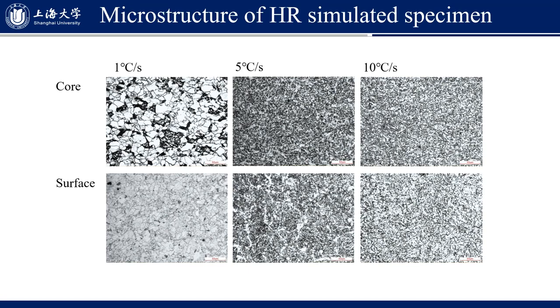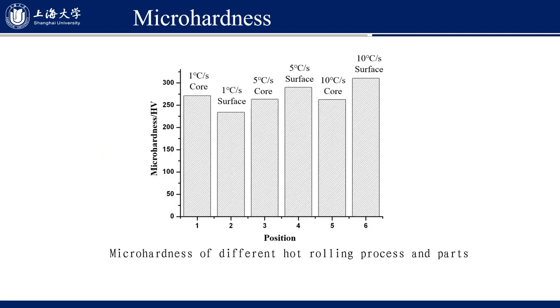Here is the microstructure of hot rolling simulated specimens, for different cooling rates, the microstructure on the surface and core part of the specimen. It is clear that the steel shows very fine grain size after hot rolling simulation. And this is the microhardness of the steel obtained after hot rolling simulation. The steel shows quite good properties after hot rolling simulation.